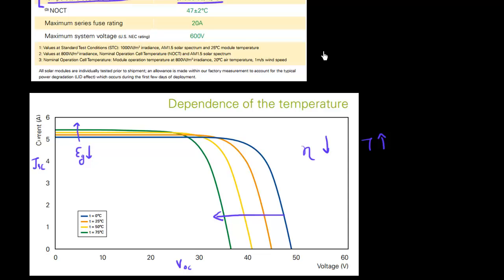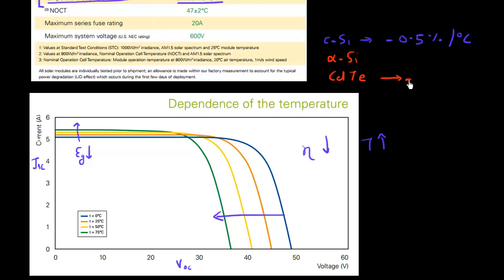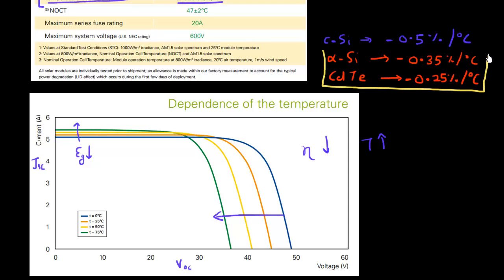This efficiency decrease is different for different kinds of cells. For crystalline silicon solar cells, it's approximately 0.5% per degree centigrade. For thin film technologies such as amorphous silicon or cadmium telluride, they fare much better. Cadmium telluride has the best temperature performance — its efficiency only decreases by about half of what happens with silicon. Amorphous silicon also comes in between. Manufacturers of thin film solar cells often tout these low temperature coefficients, especially when selling into markets where the operating temperature is quite high.